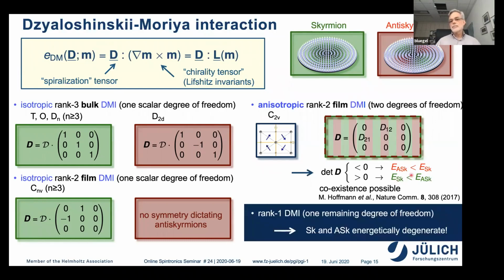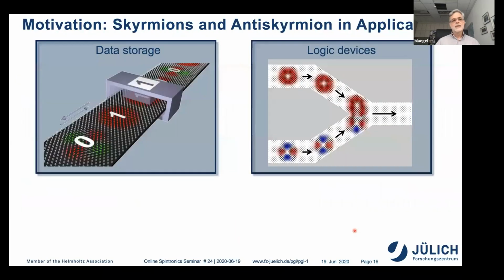And in some circumstances, what you can have is that one of these quantities is 0. And then we call that a rank 1 DMI. In this case, the skyrmion and the antiskyrmion are energetically degenerate. That means if you have such a material, you could have a skyrmion and an antiskyrmion at the same time in the material, and you could create a racetrack memory with two independent particles, which you can read out and have different resistances.